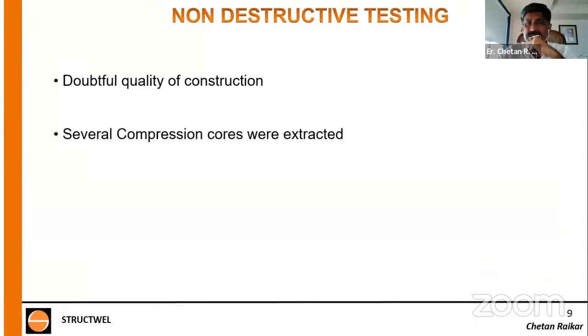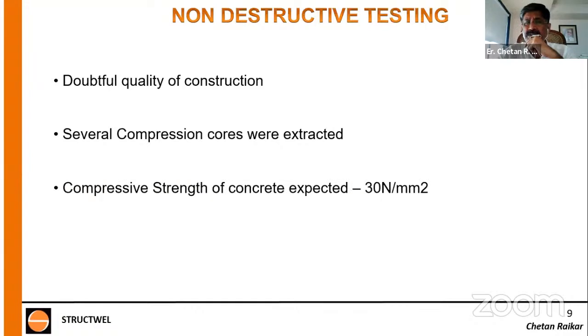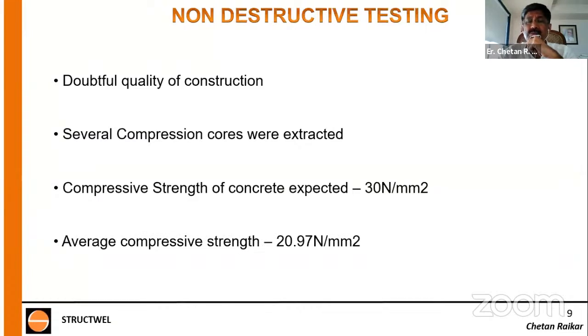Doubtful quality of construction. Though it's a great school, the construction was not so great. Why do I say that? Several cores were extracted and tested for compression. The compressive strength of concrete was expected to be 30 Newton per mm square, and on average it was about 21 Newton per mm square. So it was 2/3 of what was expected.